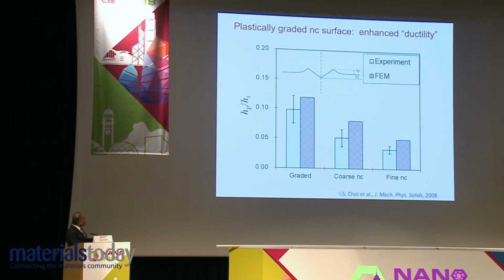What is plotted here is the pileup height over the base height, HP over HR, as a function of microstructure. This is just the nanocrystalline material only, coarse nanocrystalline material, and graded nanocrystalline material. This is experiment. This is finite element simulation of the behavior. In all three cases, we find that the graded material has the most superior response in terms of indentation response, with one indicator of ductility, which is how the material is able to pile up.